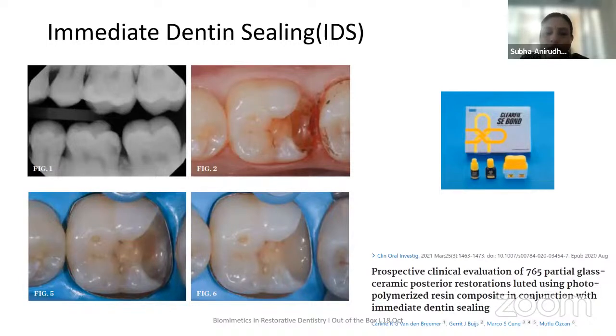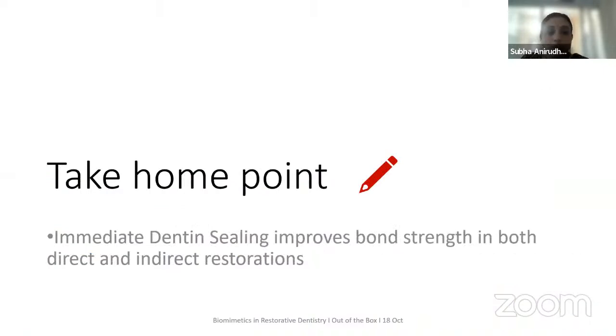A very good article by Van den Breemer et al. showed that when you use immediate dentin sealing, in clinical evaluation, it was an in vivo study, they showed that it achieved very good bond strength. The post-operative follow-up showed very little loss of restorations, which were restored after using immediate dentin sealing with photopolymerized composite resin.